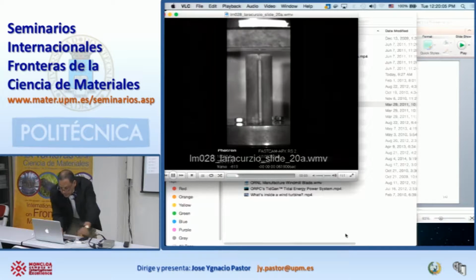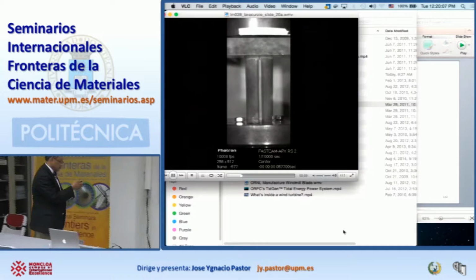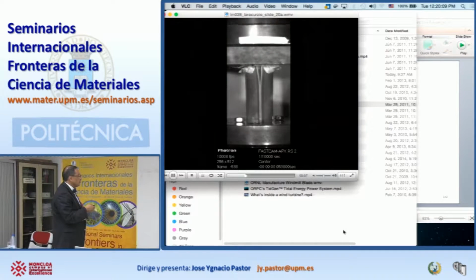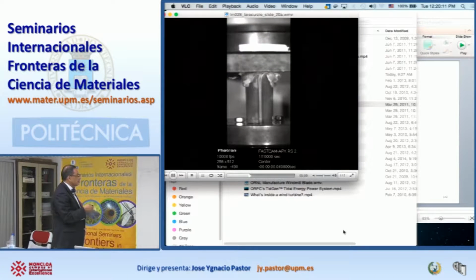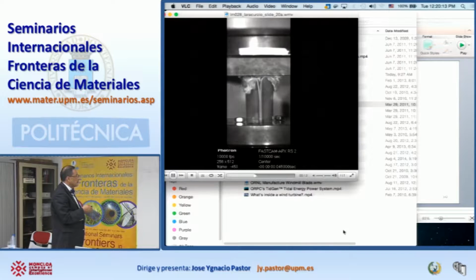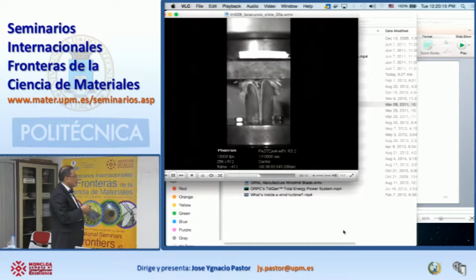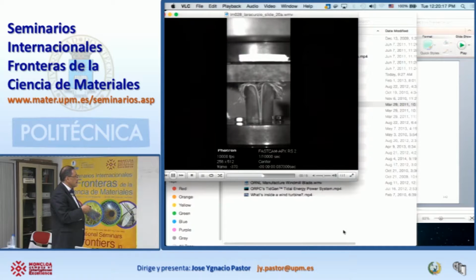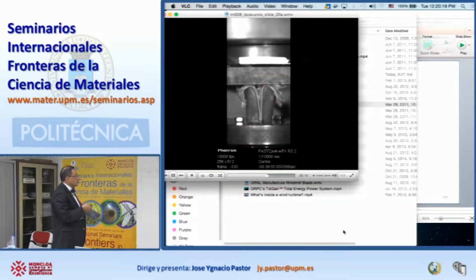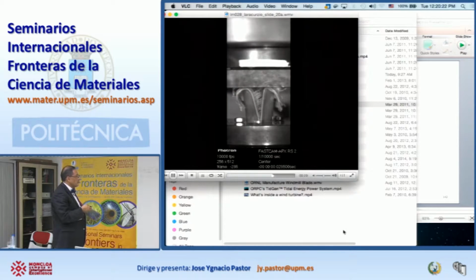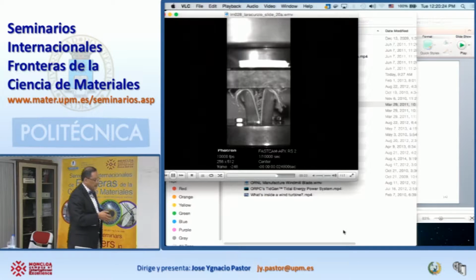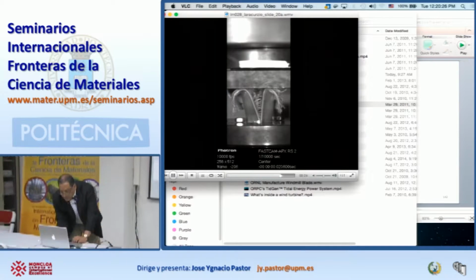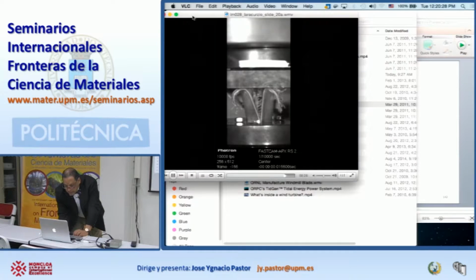So there it goes again. So this is sample A. And see how much delamination takes place? The fibers are debonding. It opens up. And what we do is we measure the force. We measure the displacement, and the area under the curve is going to give us the energy. So that's sample A.